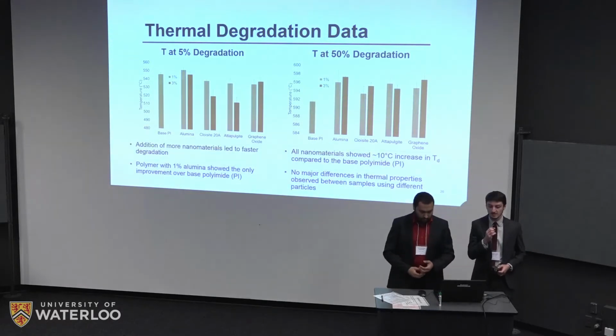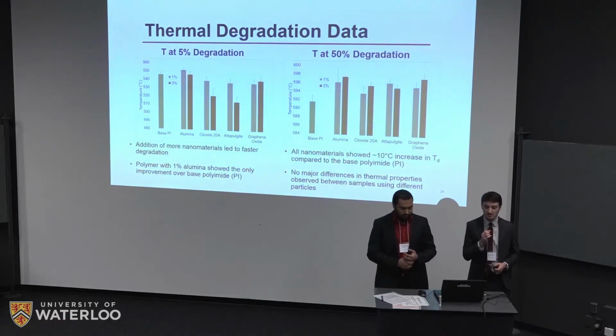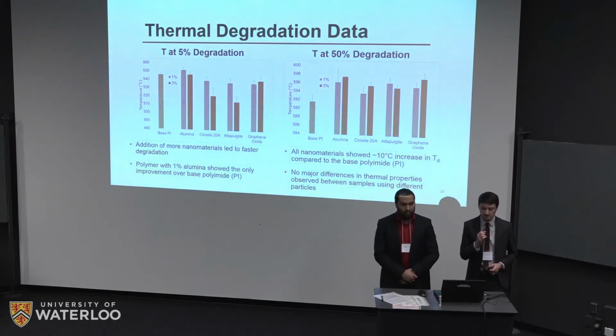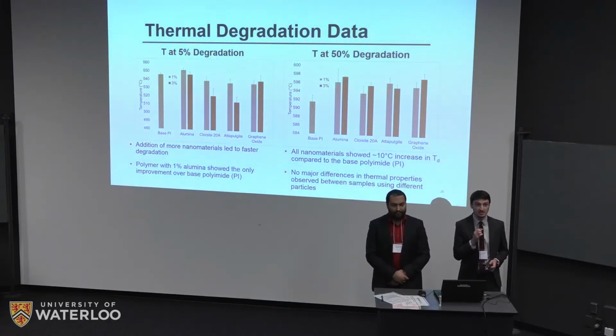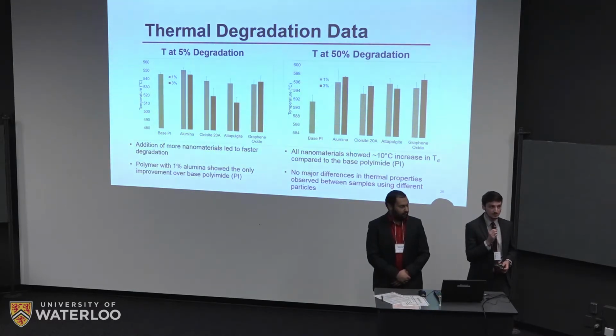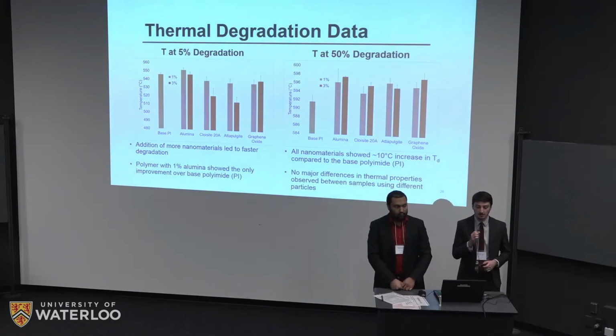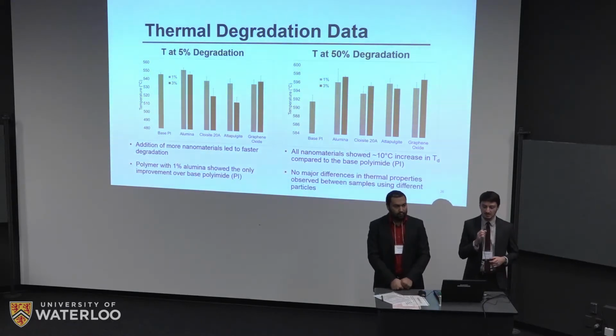So to characterize our material, we used TGA, thermogravimetric analysis, to determine the degradation temperature of our composites. We took the temperature at 5% material loss and 50% material loss in order to get an idea for the onset temperature and what the temperature was at peak degradation.